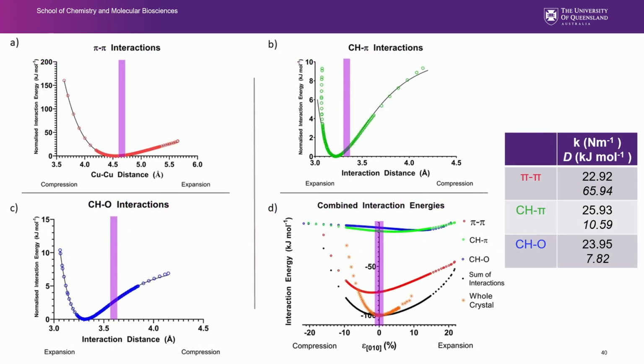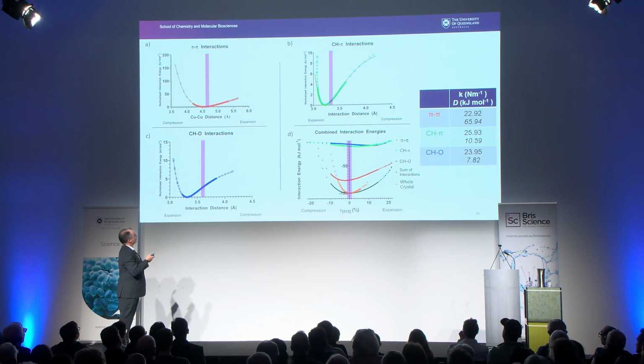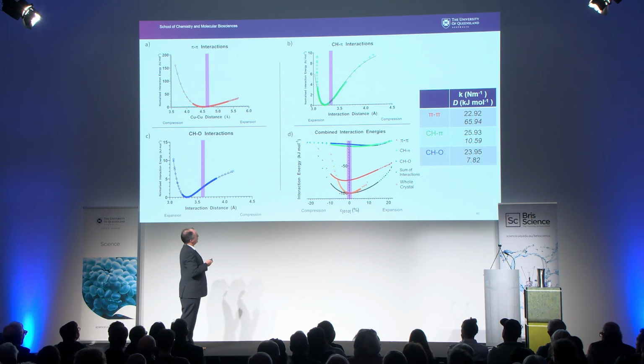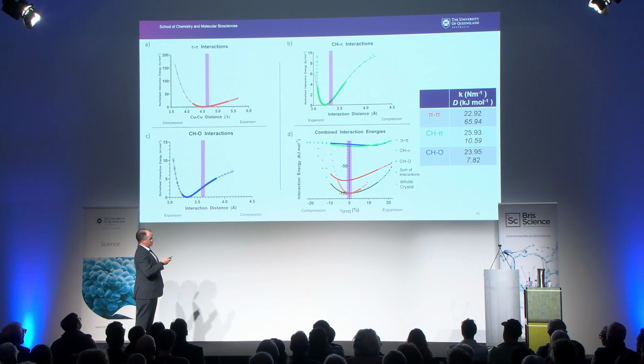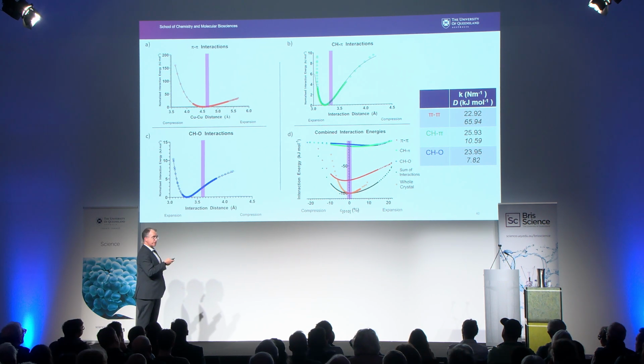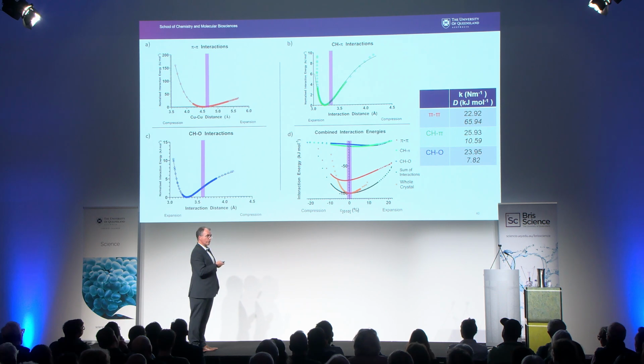So this is the sort of graph that you get out. So what we're looking at here again is just each of those interactions. So the pi-pi interaction, that CH to pi interaction, the CH-O interaction, the red, the green, and the blue, and we can see that they're behaving and we can fit them very well, just like springs. We can also see, and this purple bar represents where the elastic limit is in the crystal, we can see that they're shifted all from their minima relative to that internal position. But if we sum them all up, they form a nice parabolic shape. And that matches very well to the minimum of the whole crystal calculation. Again, from these calculations, what we can get out that's quite interesting is not just our spring constants, but the consequence of that is by integrating under the curves, we can get out the energy that's stored in each particular interaction.